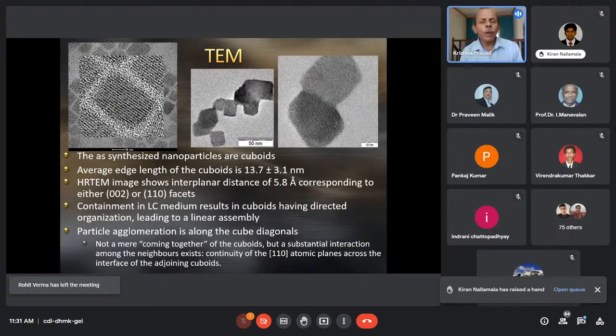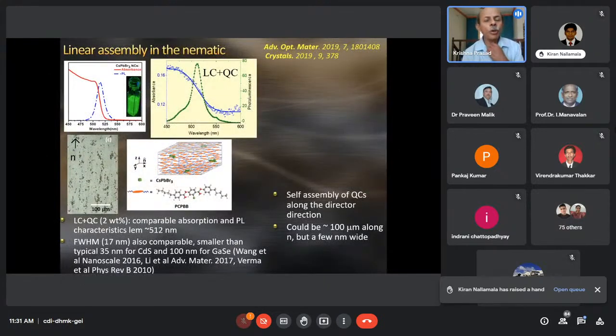And these quantum cuboids, when you put them in liquid crystals, they start organizing themselves into a linear chain, as you would see in the middle transmission electron microscopy image. So they arrange themselves along their body diagonals and lead to some kind of a chain. Apparently, since you are talking about TEM, it appears to be happening only at a local level. But actually, when you view the cesium lead bromide incorporated into liquid crystals by doing a proper combination of the surface nature of the cesium lead bromide and the kind of liquid crystal that you need to have, you can actually start seeing chains of cesium lead bromide quantum cuboids lined up along a particular direction.